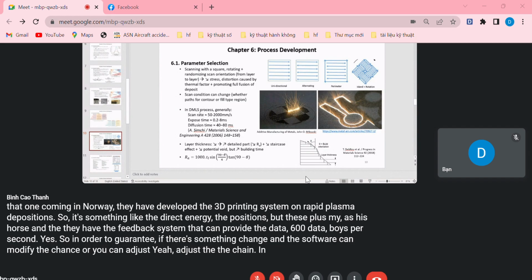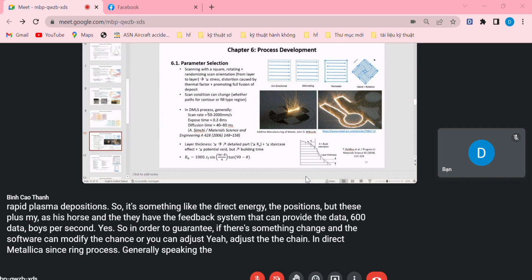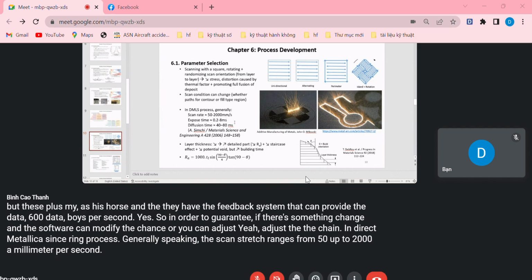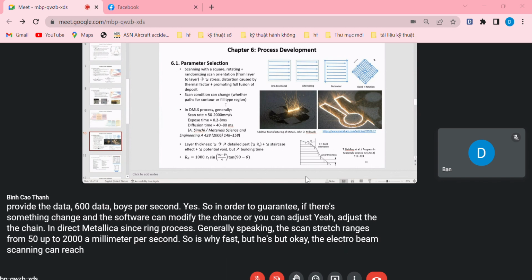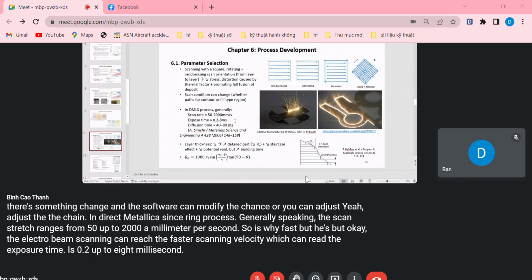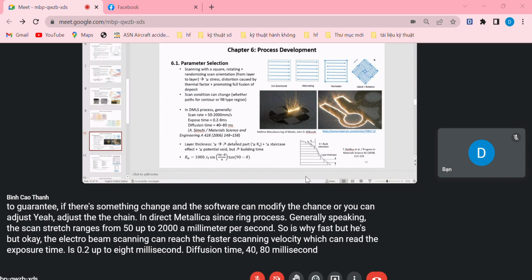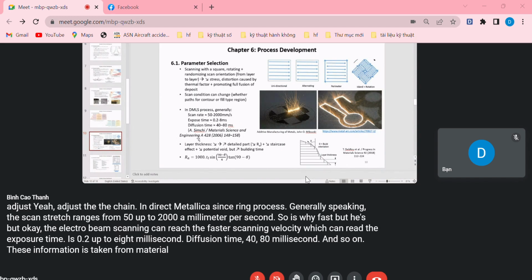In direct metal laser sintering process, generally speaking, the scan ranges from 50 up to 2000 millimeters per second. It's quite fast, but electron beam scanning can reach faster scanning velocity. The exposure time is 0.2 up to 8 milliseconds. Diffusion time is 40 to 80 milliseconds, and so on. This information is taken from the Materials Science and Engineering journal written by Simchi.